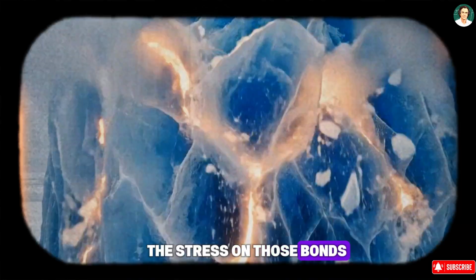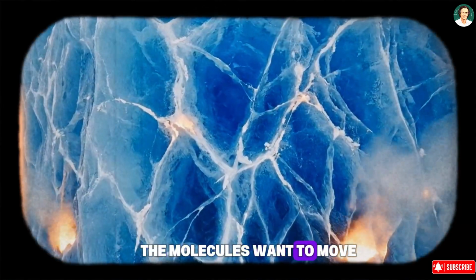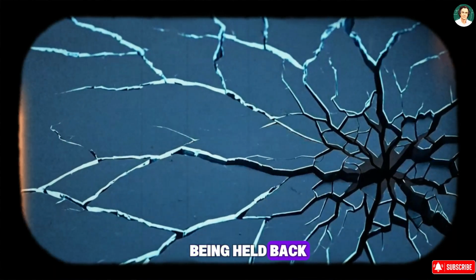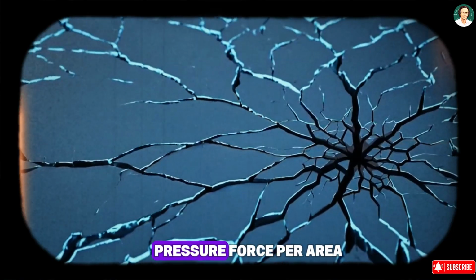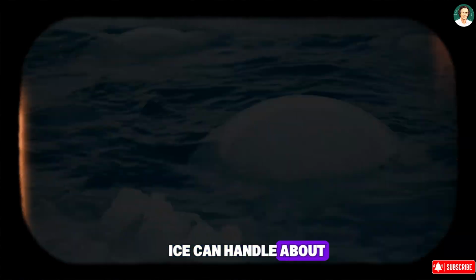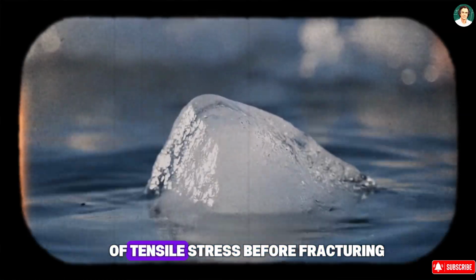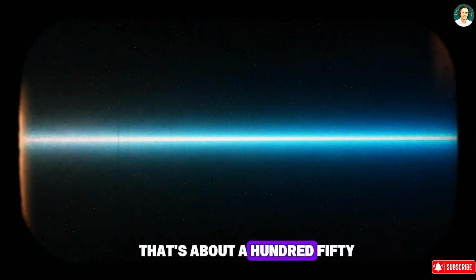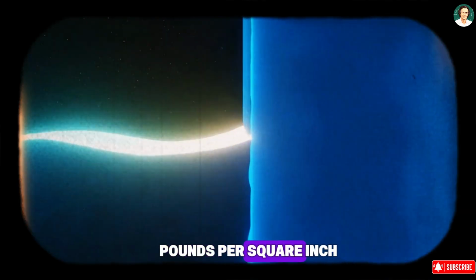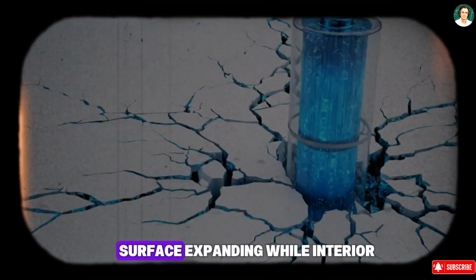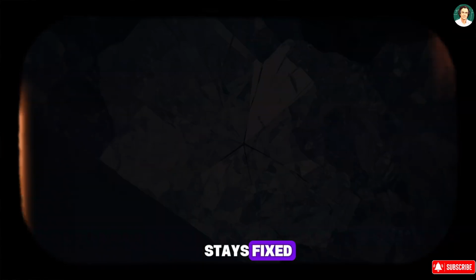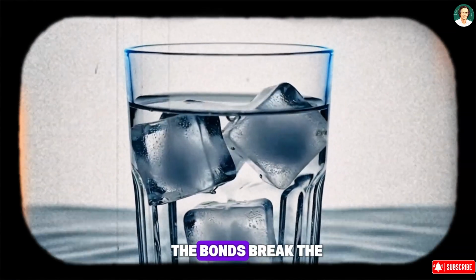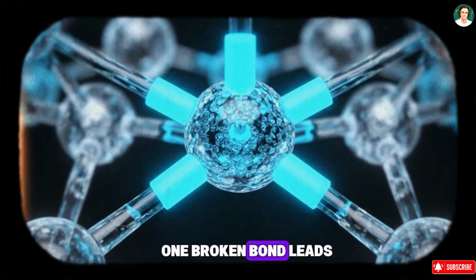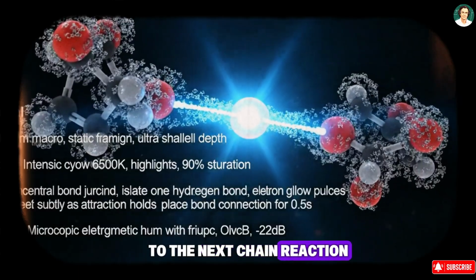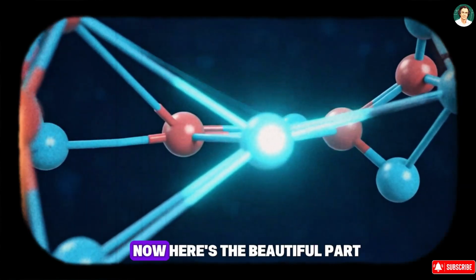The stress on those bonds depends on how much the molecules want to move versus how much they're being held back. It's measured in pascals. Pressure, force per area. Ice can handle about 1 to 3 megapascals of tensile stress before fracturing. That's about 150 to 450 pounds per square inch. When you create that temperature gradient, surface expanding while interior stays fixed, you can easily exceed this. The bonds break, the crystal fractures, the crack propagates. One broken bond leads to the next. Chain reaction, milliseconds. Done.